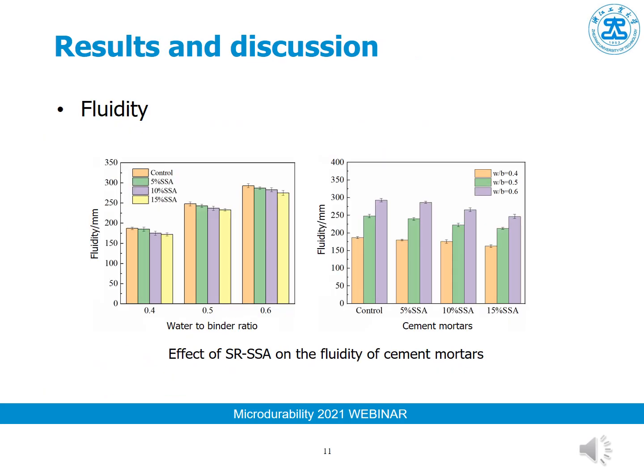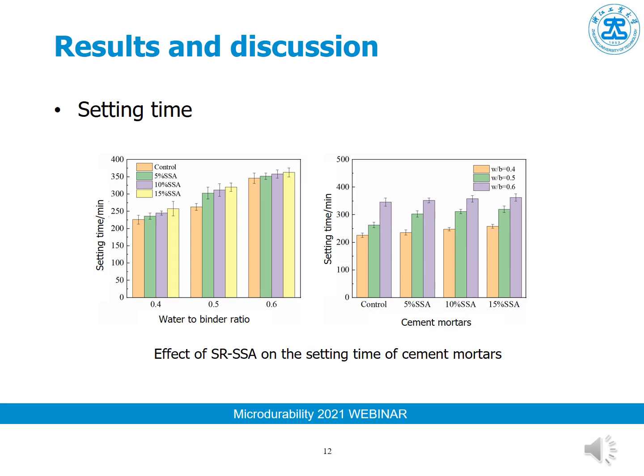This is the test results for the fluidity tests, and we can see that the addition of this ash reduced the fluidity of the cement mortar, and more ash resulted in more fluidity reduction. Here are the setting time results, and we can see that with the addition of the sulfate-rich sewage sludge ash, the setting times of the mortars were retarded. And this is due to the presence of the zinc and phosphorus elements in this kind of ash.